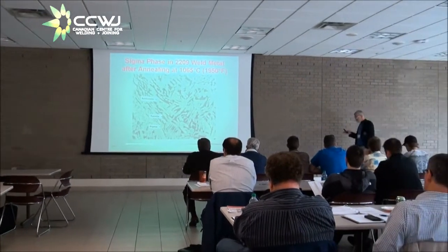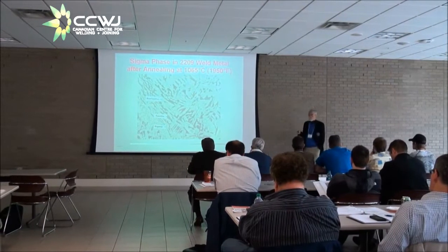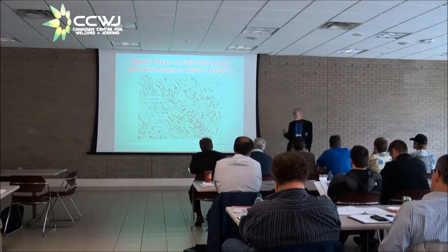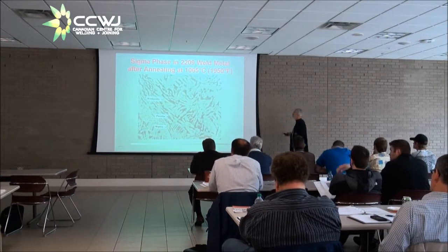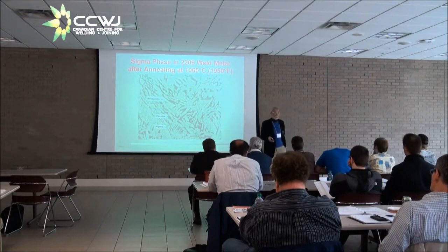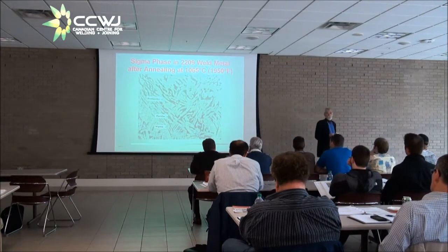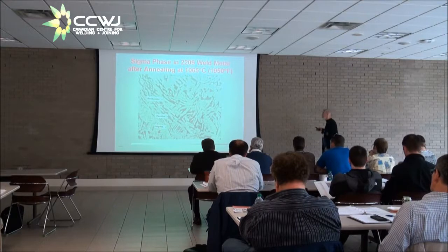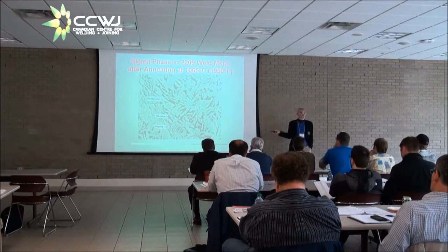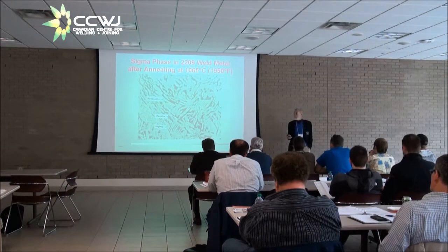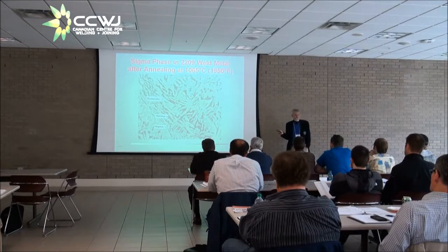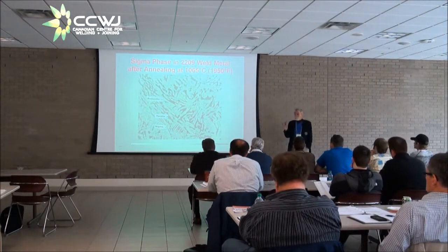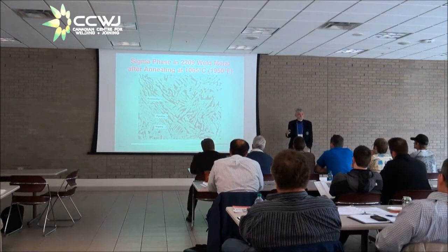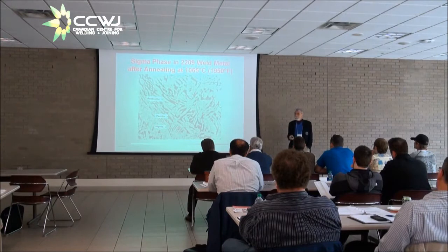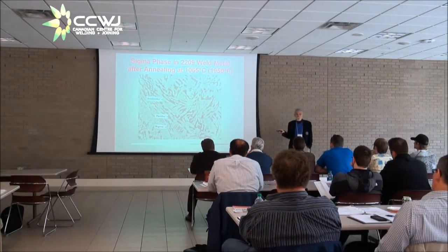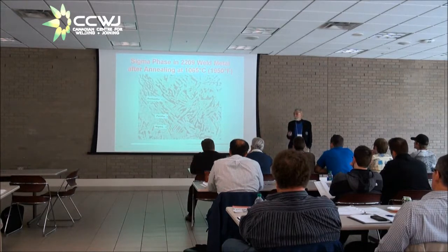So I have a technician in what we called affectionately the busting lab. That was the lab where we broke things, like tensile specimens and impact specimens. And I asked him to break specimens at room temperature to start out. So he got this sample. He broke the first couple impact specimens at room temperature, and then he came running down the hall to my office. He goes, Doc, you got to see this. You got to see this. What? So I go down to the busting lab, and he says, now watch this. And he puts the impact specimen in the impact machine at room temperature. Hits the hammer. Now, when you got a good impact specimen, it's going to go thud. This one went blink.